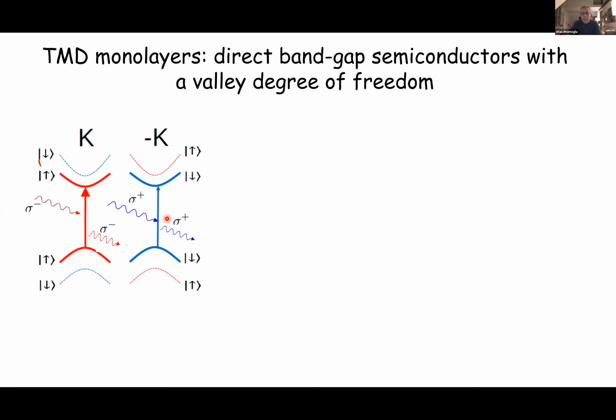And so indeed you can consider not only the bright excitons that are necessarily intra-valley excitons that can be generated, but if one does a photoluminescence study, that is, applies a high energy laser and lets the carriers relax, then one could end up in, let's say, inter-valley excitons where the electron and hole live in different valleys. And these, as you say, have comparable binding energies. Actually, inter-valley excitons have lower energy because they do not have electron-hole exchange interaction. So bright excitons do have what we describe as the short-range electron-hole interaction. So basically, the way to think about it is that there is mixing between the conduction and valence bands, and to the extent that we're dealing with excitations with the same spin, then there will be an exchange correction.